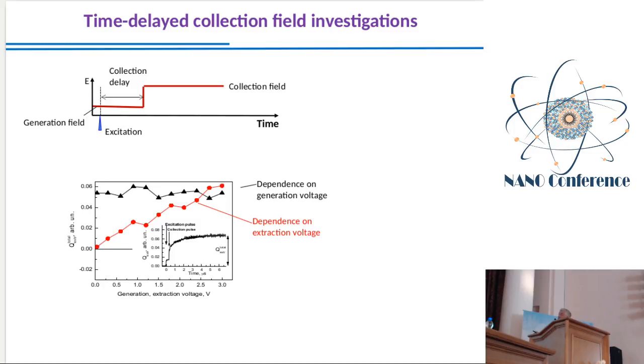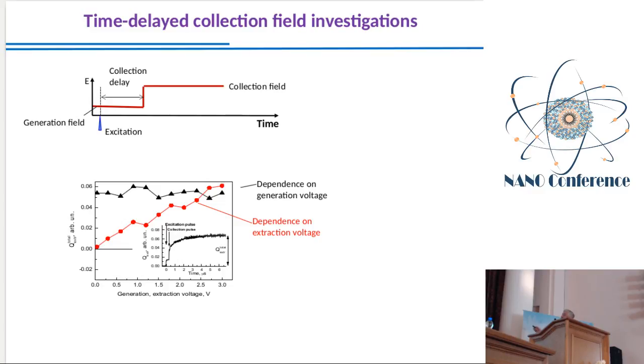And so here we change the generation voltage, so we use not 0 volts, but some generation voltage, and we look at the photocurrent when it's collected by the collection field, and we see that nothing happens by changing this generation field, so it means that charge carriers are generated spontaneously. They do not need the assistance of the electric field. But for extraction of charge carriers, we need, in fact, a strong electric field. So here we change the collection field, and the dependence on the extraction voltage shows quite a strong dependence.